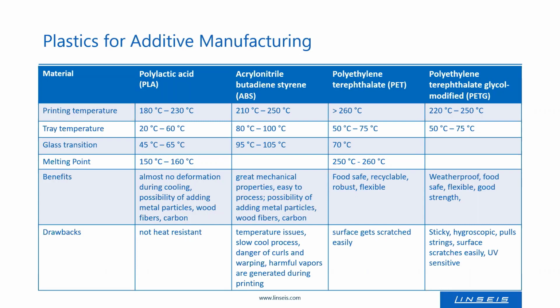So the 2 most common polymers or plastics used for additive manufacturing are PLA and ABS. PLA is made out of fermentable plant starch, for example, corn or sugarcane, and thus it is a bioplastic and is biodegradable. PLA is rather easy to print. Only low temperatures are needed, so the printing temperature ranges from 180 to 230 degrees Celsius. The actual printing temperature also depends on the manufacturer of the filaments. PLA also has fast cooling and solidification times, so the printing process is also rather fast.